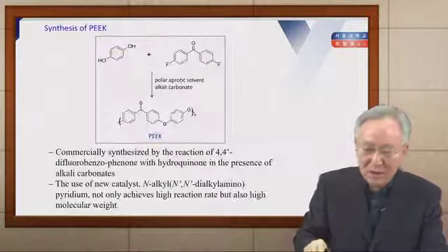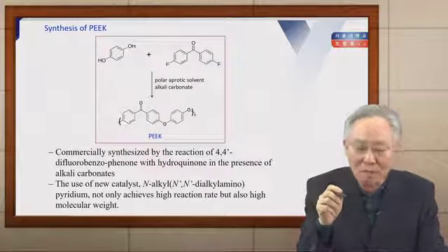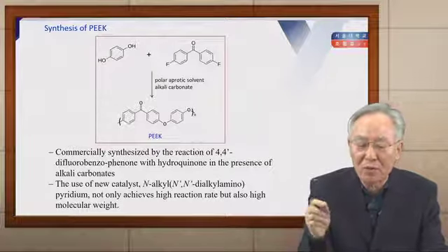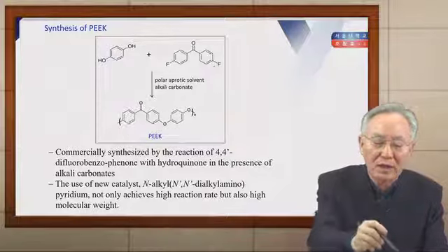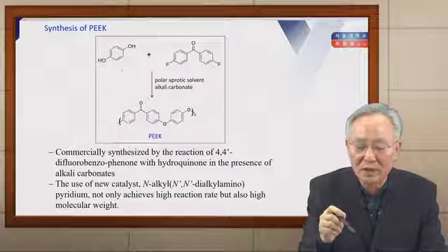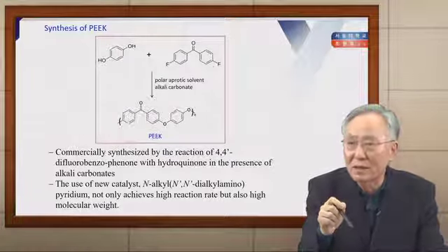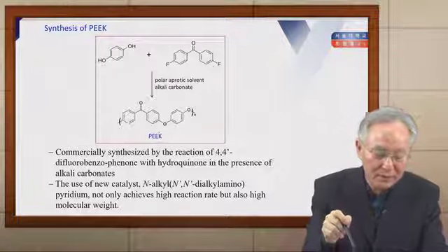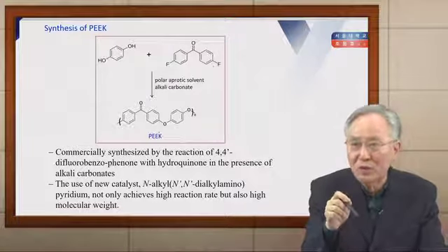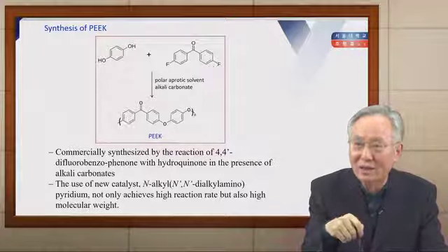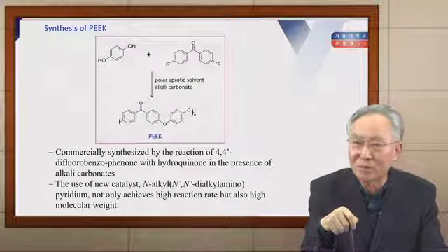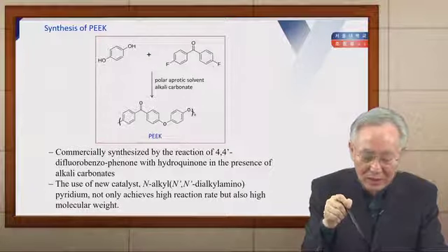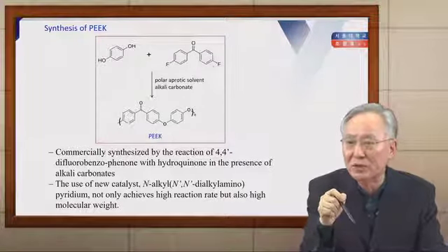PEEK has been synthesized by reacting difluorobenzophenone with hydroquinone in the presence of alkali carbonate as catalyst in a polar aprotic solvent, giving the polyether ether ketone structure. Using a new catalyst such as N-alkyl-N',N'-dialkylaminopyridinium can achieve not only high molecular weight but also a high reaction rate.